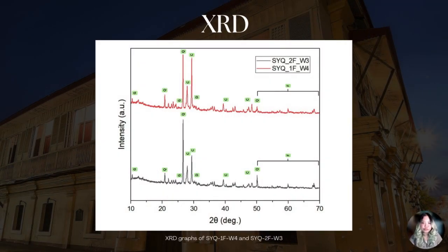The peaks around 29.4 degrees for calcite and 26.6 degrees for quartz prove their presence, as they were used as an aggregate. Dolomite peaks at 30.9 degrees suggest impurities or the use of dolomitic lime. Smaller peaks at 40 and 47 degrees are secondary calcite reflections, supporting its primary role. Gypsum at 11.6 and 20.7 degrees was detected, which is likely from reactions due to environmental conditions, where over time, lime plaster can absorb sulfur from the environment and form gypsum, while feldspar at 50 to 70 degrees may be from aggregates. This mineralogical makeup is consistent with traditional lime plaster, as peaks indicate calcite as a primary binder.